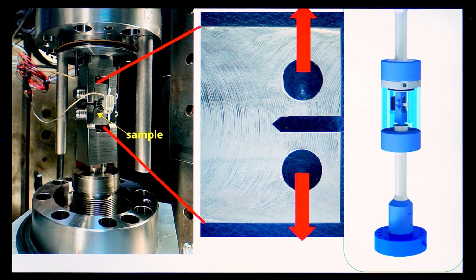Okay. And what kind of material would withstand that more? At the moment we test a lot of ferritic materials, because these materials are used for the pipelines. But you can also use a hardened material. Yes, but then we have the problem that hardened material is more critical if there is a crack inside. Okay. Wow.